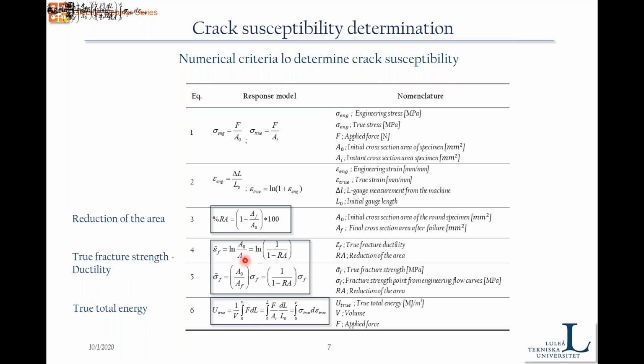That's why we were combining it with these other 2, the true fracture strength ductility and also the true total energy. It is important to mention that the true fracture strength ductility is valid after the necking, while these other 2 models are only valid up to the onset of the necking. So this combination of criteria was considered new for determining crack susceptibility, and it can give more accurate results.